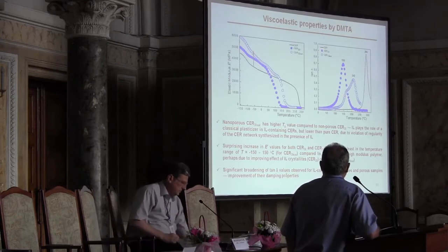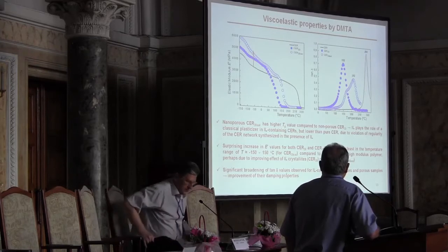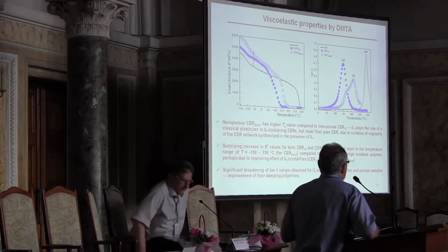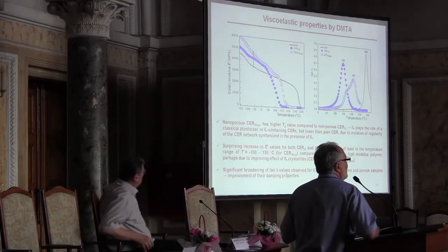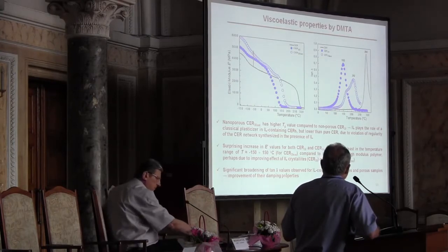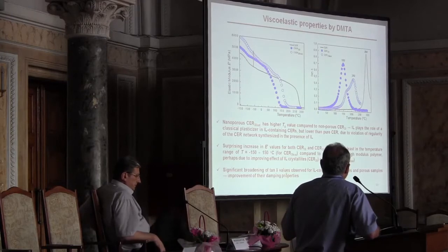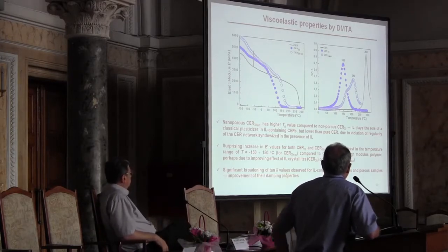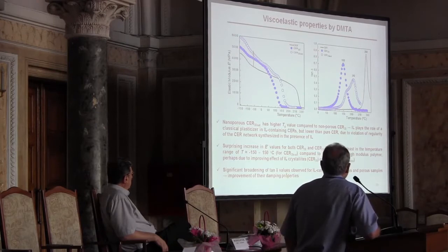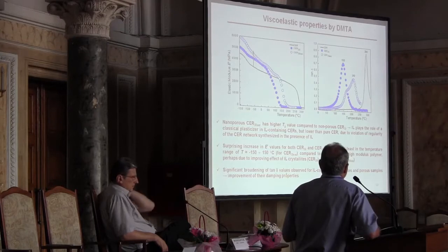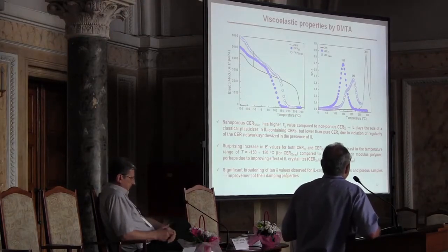Now about viscoelastic properties by the DMTA method. What is interesting here is that CER networks are well known as high modulus networks, and in our case, the addition of ionic liquid and the introduction of pores increased the elastic modulus even more, at least in the temperature range from minus 150 to plus 150 degrees centigrade. And the glass transition temperature was found to be lower for the nanoporous network compared to the pure network, but higher compared to the precursor containing ionic liquid.